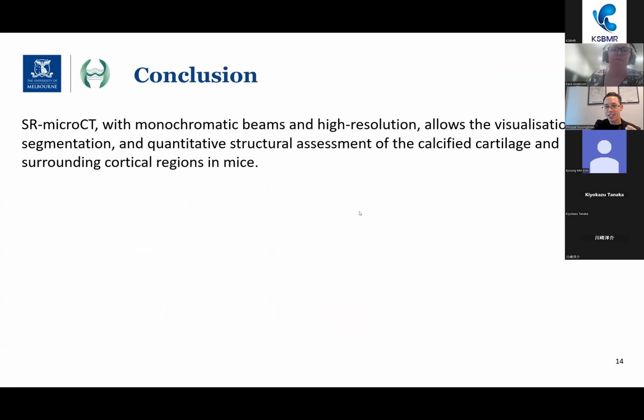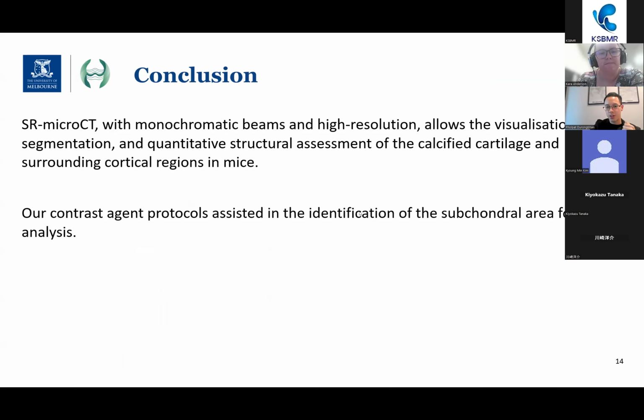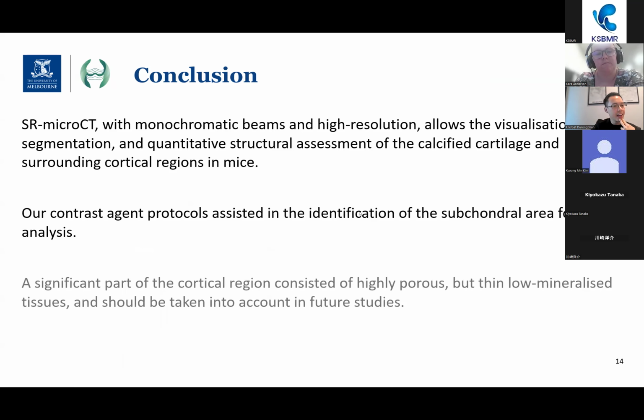Just a rough quick conclusion is that SR micro CT, synchrotron radiation micro CT with monochromatic beams and high resolution, allows visualization and quantitative assessment of calcified cartilage and other surrounding cortical regions in mice. And other tissues, really. The image I showed on the cover by Dr. Shiba was actually from a human biopsy sample. And our contrast agent protocol has shown that we can identify the subchondral area, that is the region immediately underneath the cartilage, for analysis. And a significant part of the cortical region can consist of highly porous but low mineralized tissue, which we should take into account, even though we cannot see it in micro CT, but to be aware of this difference in level of mineralization.